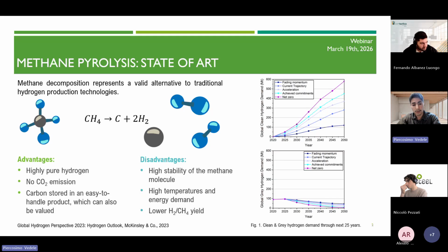The main advantages of this process are related to the production of highly pure hydrogen, of course depending also on the conversion of the reaction, the absence of CO2 removal stages, and an easy way to store the carbon produced through this reaction. Of course, the main disadvantages are related to the high stability of the methane molecule. So it is an endothermic reaction, and high temperatures and high energetic demand are required to conduct it, with a lower hydrogen to methane yield compared to state-of-the-art competitors, such as steam methane reforming.